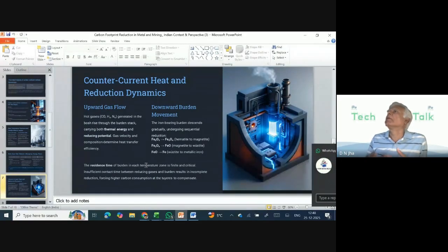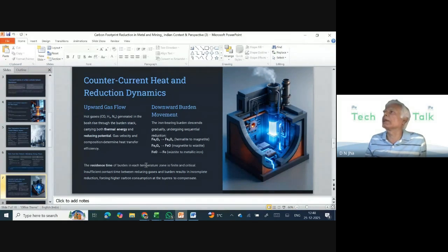If that is happening, then what do we have to do? We have to provide for more reducing gas concentration. So, how do we provide more reducing gas concentration? We'll have to increase CO and hydrogen in the gas that we are generating at the Bosh. So this is an increase in the partial pressure or concentration of CO and hydrogen in the Bosh gas.